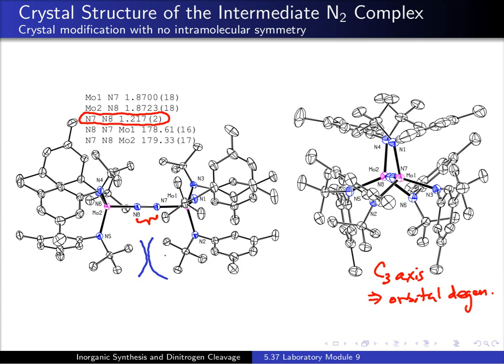And actually, if we use substituents that are larger than tertiary butyl that would come into this space, we can completely shut down the formation of any bridging N2 complexes. So the tert-butyl group selection here is really important because it's big enough to keep the two molybdenums from coming together and forming a molybdenum-molybdenum triple bond, but it's also small enough to permit the formation of an N2 bridge between the two molybdenum centers. So that structural attribute is nicely illustrated in this crystal structure.